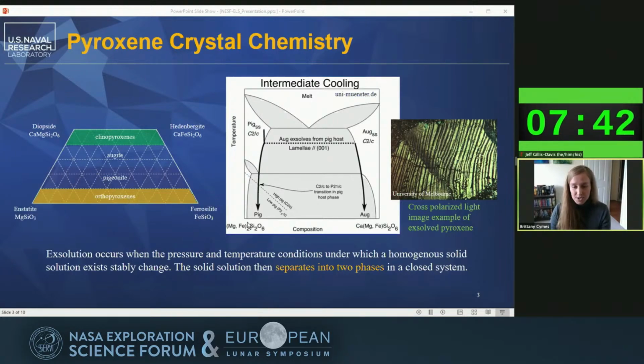Using this phase diagram between orthopyroxene and clinopyroxene as an example, you can see that when a stable pigeonite solid solution cools, it reaches a univariate curve, and then the solid solution separates into two more stable coexisting pigeonite and augite phases. And this results in something that looks a little like this cross-polarized light image here. So there's our two phases. And as you can see in the center of this diagram, the augite lamellae form parallel to the 001 plane. So these chemically distinct domains are not random. They share symmetry components. So now we've got our second component of controlling our crystal structure.